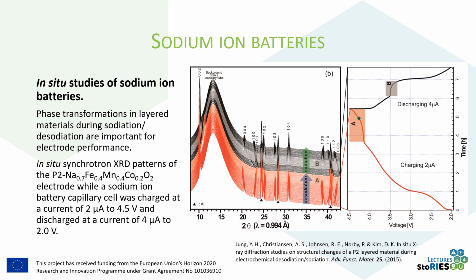Here's an example of an observed powder diffraction pattern during charge and discharge of a layered cathode material. So we see the diffraction pattern and how the diffraction pattern changes during charge and discharge. The charge-discharge curves are shown to the right with a vertical time axis corresponding to the diffraction pattern.